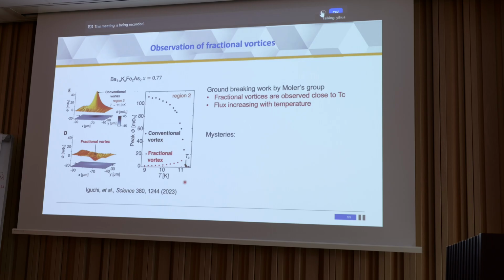However, there are also some mysteries, even though it has stirred a lot of interest within the community, including us. They have only observed one component of the fractional vortices. As I mentioned earlier, the total fractional vortices should sum up to phi naught, but the rest is still missing from their measurements. And also, because this fractional vortex is decreasing in amplitude with decreasing temperature, it is very difficult to observe fractional vortices at temperatures away from Tc. So these are the motivations for us to study this material further.